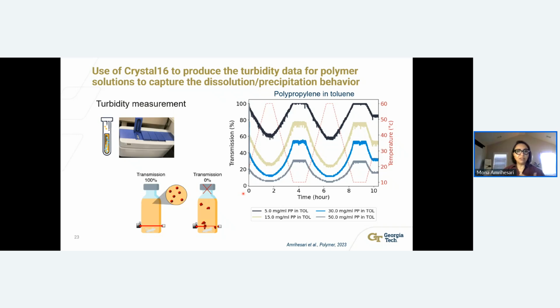So as you can see, the Crystal 16 can help us to monitor the phase change during the change in temperature in a thermal method. So we introduced some cutoffs to this system and said, okay, if the transmissivity, which is the outcome of the Crystal 16, is above 85% for a solution, let's categorize that as a soluble material. If it's below 10%, let's have that as insoluble. And between 10 to 85, let's classify that as partially soluble, because the solution does not go to the fully clean state, the transmissivity dropped to a lower value a little bit, but it's clear for most part. There are still some precipitate floating in the vial.